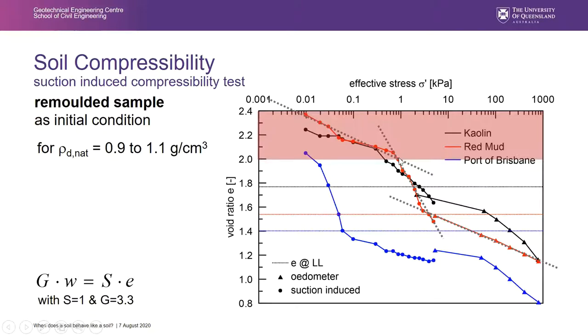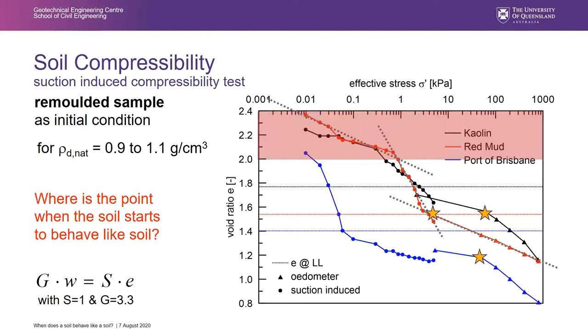At the moment, we are not fully through with our investigations concerning that. But at the moment, we think that we overcome here hindered sedimentation. Because when you think about it, this void ratio means that we have double the volume of voids than the volume of solids. We can't really assume that the particles really touch each other, but they interact through the bound water phase. And from a certain point of stress, we then get this kind of collapse-like densification until we probably reach exactly that point where particles start to transfer stresses. So one possibility to say the soil starts to behave like a soil is when we have this transition from the one behavior to the other.